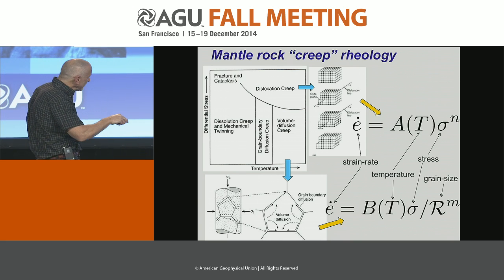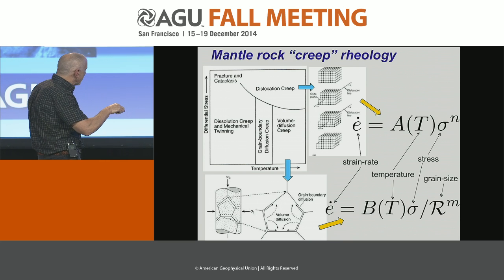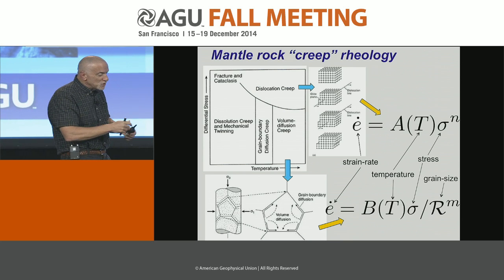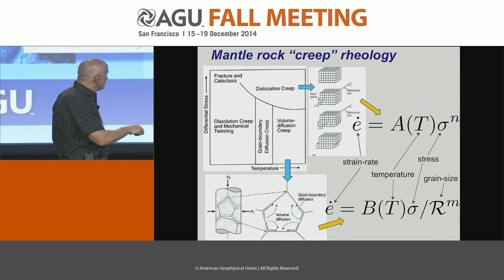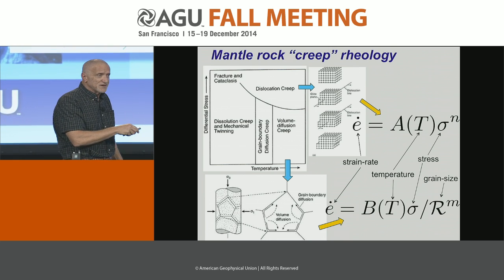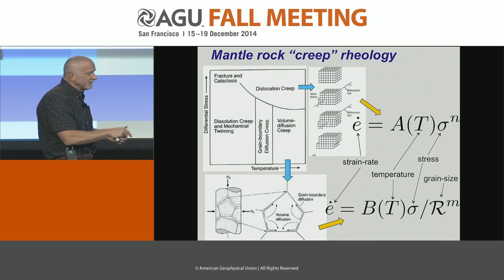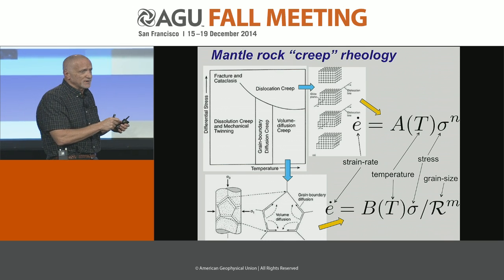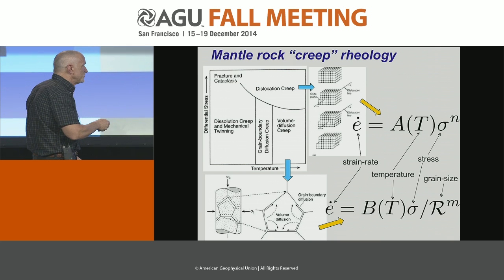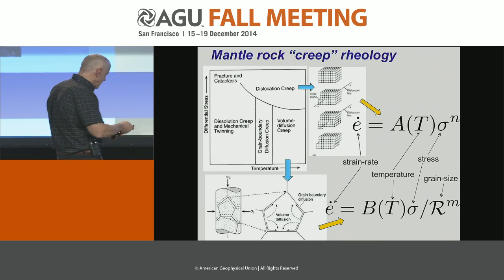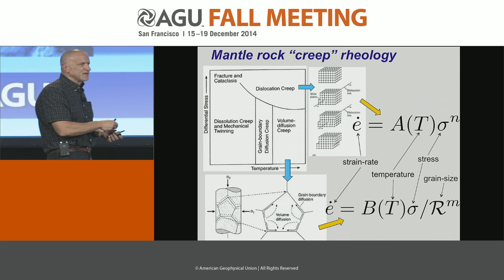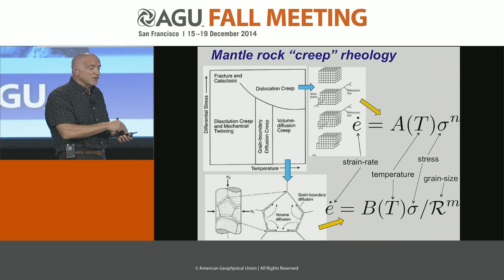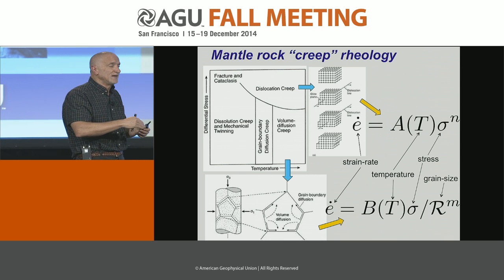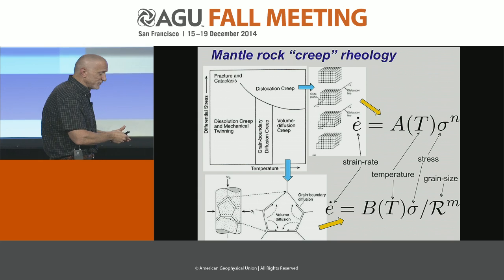Diffusion creep is linearly dependent on stress. Strain rate and stress are, in a Newtonian sense, linearly dependent on each other, but it's strongly dependent on the grain size. The smaller the grains are, the easier it is to deform, because the easier it is to drive diffusion from compression to tension. But both of these are very strongly temperature dependent, meaning that the cold lithosphere near the top of the mantle tends to be very stiff intrinsically.